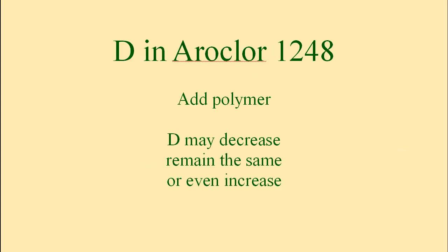We now come to the effect of adding a polymer to an extremely viscous solvent, namely Aroclor 1248. On adding the polymer, well, it depends which polymer you add. The diffusion coefficient of the solvent molecules may decrease, it may remain the same, or it may even increase, that is, the added polymer may act as a plasticizer for the solvent.